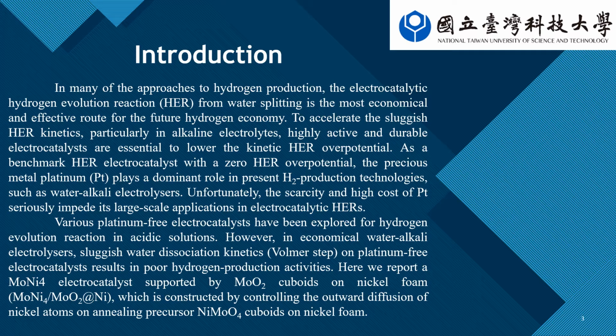And in this paper, the authors report a MoNi4 electrocatalyst supported by MoO2 cuboids on nickel foam, which is constructed by controlling the outward diffusion of the nickel atoms on annealing precursor nickel molybdenum oxide cuboids on nickel foam.